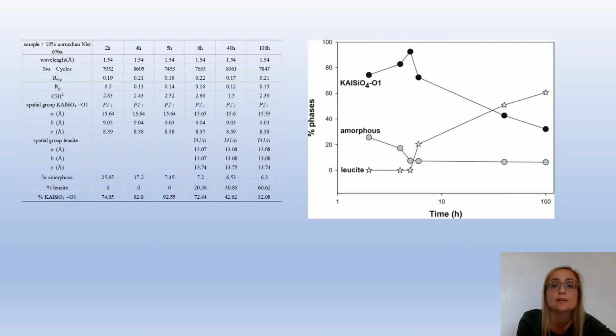On the right, there is the volume or weight fractional change in the participating phases as a function of time. The most notable changes occur over the first 2 hours of the synthesis, as nearly 75% of the amorphous phase is transformed directly into KAlSiO4-O1. From 2 to 5 hours, this transformation appears to slow down, during which the maximum KAlSiO4-O1 fraction of 92.55% is reached before any leucite is detected. After 5 hours, the KAlSiO4-O1 phase is continually replaced by leucite, even though about 6–7% of the sample remains amorphous. At 100 hours, the sample is dominated by the presence of leucite.